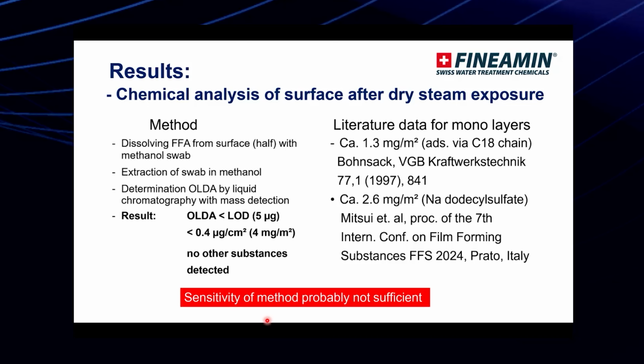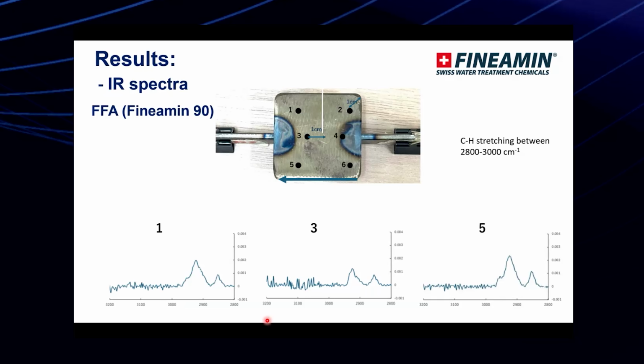Dr. Wolfgang had to make some comparison with the literature data on monolayers from different publications. So what we see is that the detection limit is not high enough. So we have to go to the next method, which is more sensitive. In this case, we're using infrared spectroscopy, and here we see results of the carbon hydrogen bond stretching. So in this case, there is a clear absorption.